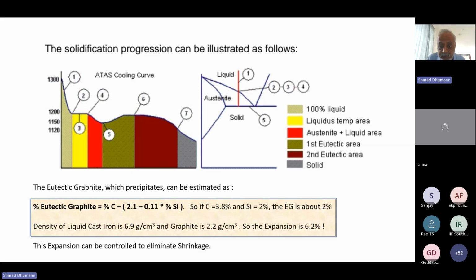And how much is the expansion? For this particular case, I have calculated. When carbon is 3.8%, silicon is 2%, your eutectic graphite is 2%. When all that eutectic graphite precipitates, it will increase the volume of the liquid by 6.2%. So just understand that the solidification shrinkage is between 4 to 5%, but the effect of graphite precipitation is 6%. So when your graphite precipitates fully, nicely, accurately, soundly, then this graphite expansion can fully control or eliminate your solidification shrinkage. That is the learning point, the takeaway from this particular slide. And we can all work out how much the expansion is, and whether this expansion can help us to counter solidification shrinkage in our casting.